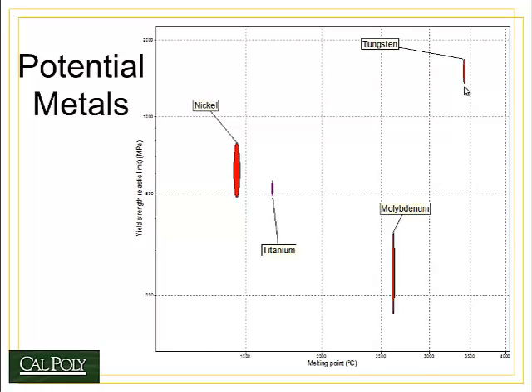The problem with tungsten is its extremely high melting point — how are you going to process it into the shape of a turbine blade? How would you liquefy tungsten and cast it into a mold without damaging the mold? Molybdenum is another choice because it has a high temperature, but it's not very strong. Titanium can catch fire and react to form titanium dioxide, so that's not a good choice for a jet engine. It turns out the ideal choice is nickel and alloys of metals based on nickel.